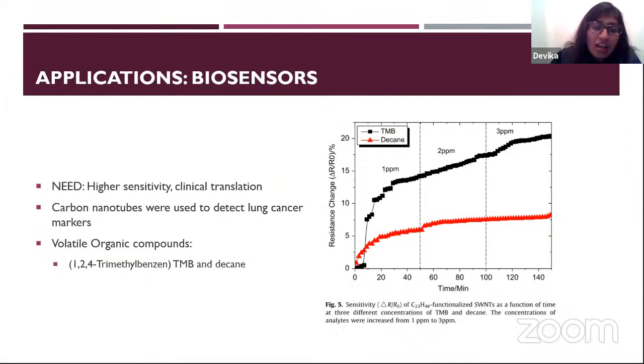And using these functionalized carbon nanotubes, they increased the concentration of the analytes, the markers, and they saw that these nanotubes could detect it as it increased, at least for the TMB marker. The decane kind of saturated after a point, but the TMB increased with increasing concentration, which is a great thing because these volatile organic compounds are supposedly in the air, so as you breathe, or in the saliva, so it would be very clinically relevant to have something like this.